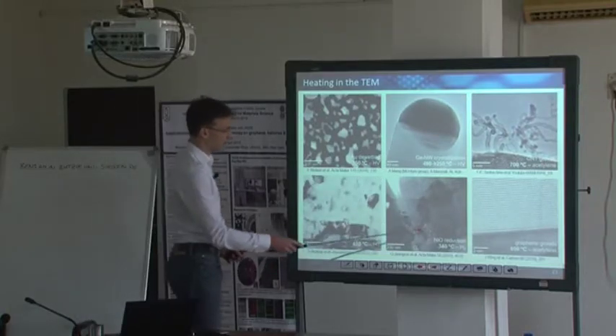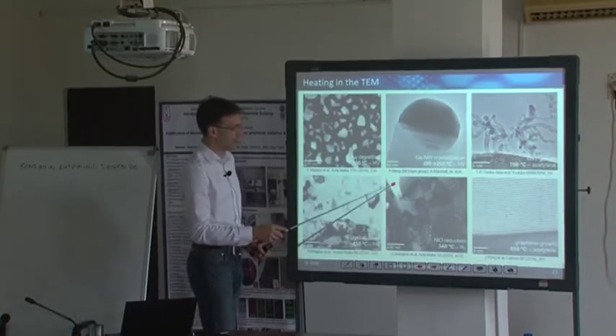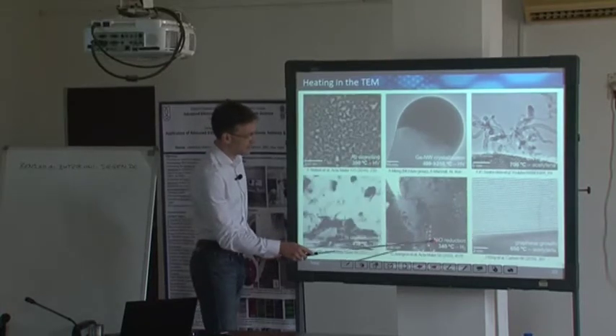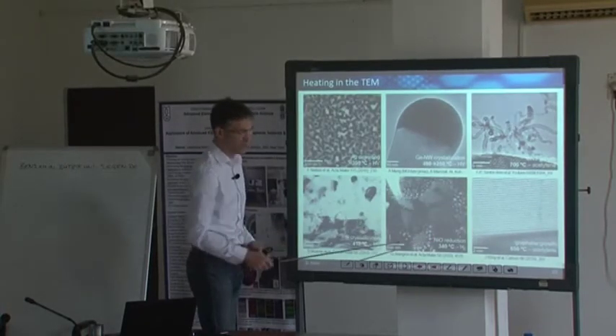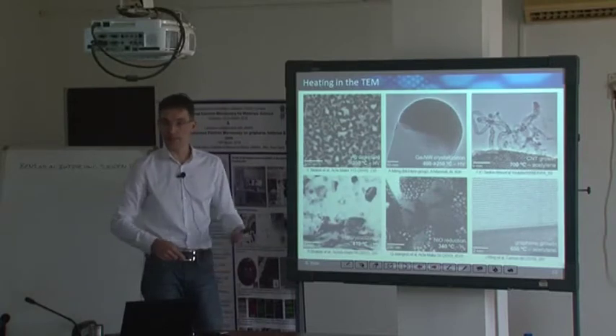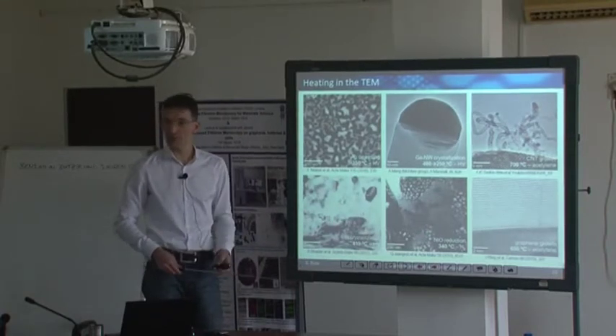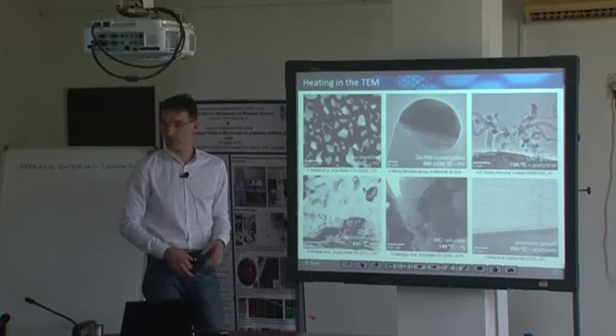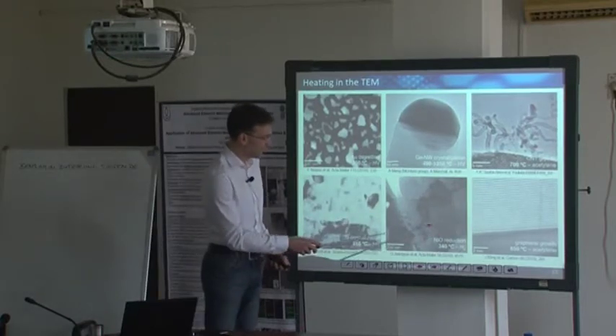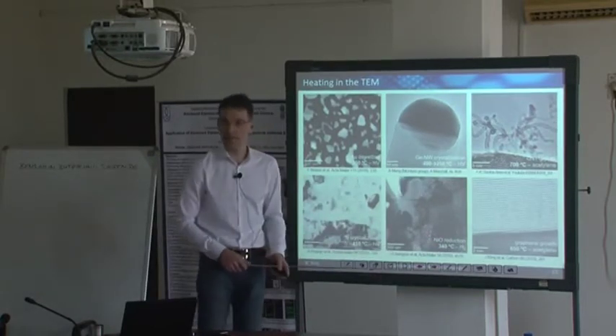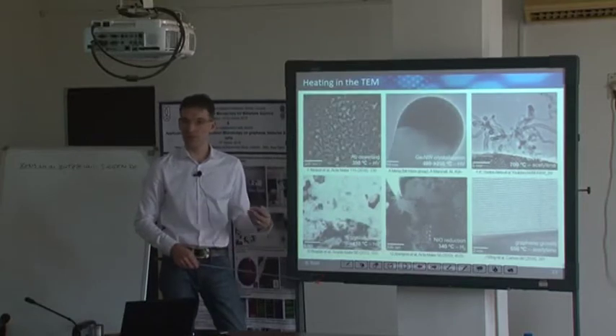Yeah, in many effects, this is like the bright field image here. You see, this is the nickel. If you reduce nickel oxide to nickel, you lose volume because you lose all your oxygen, so the volume is smaller. This is why pores form in this reduced nickel oxide. But you have to think about what happens if you re-oxidize that.